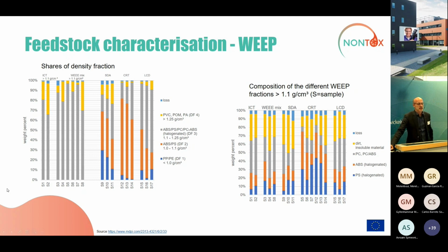The majority is here for the gray fraction of the ABS, PS, PC ABS. And the bad news is that this is a fraction which contains bromine. Let me further show you which polymers are expected in such fractions higher than 1.1. You see that we have shares of PS, of ABS, and also of PC ABS, but they do not make up 100% of this fraction.